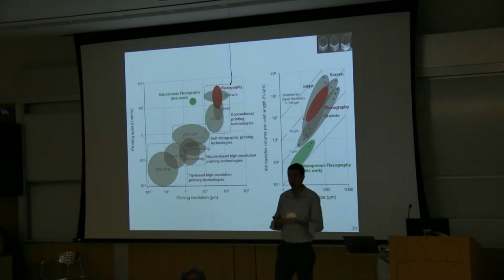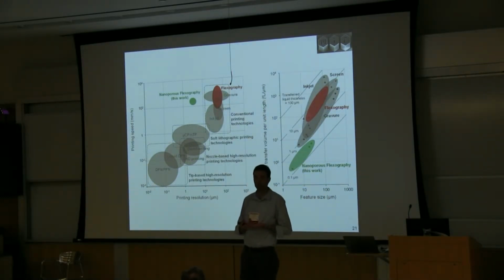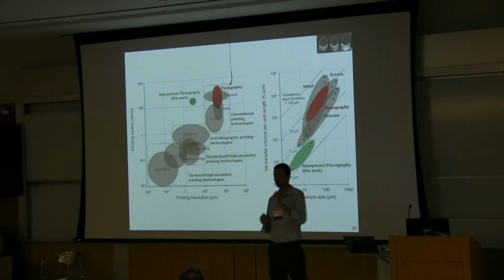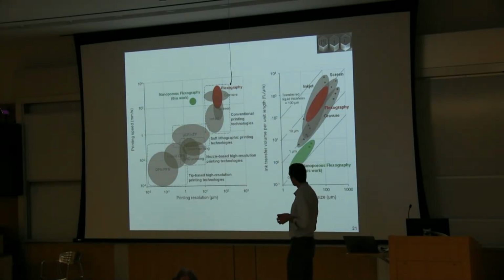Not only things like cost, but rate and resolution, which can be lateral resolution and thickness resolution. And so far our process compares in the following way. We found that using these nanoporous stamps, we can print features, and this is the best we've achieved, about an order of magnitude finer than existing flexographic technology using rubber stamps.